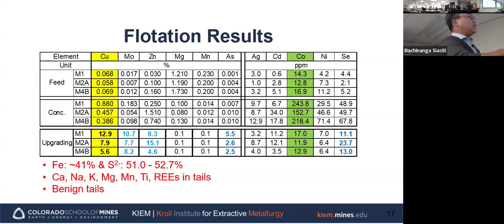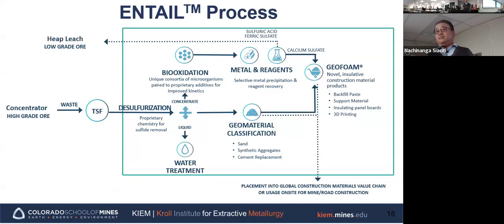And then, as you can see, I mentioned arsenic. Arsenic comes to the concentrate. So it is concentrated in sulfide and pyrite, along with moly, zinc, selenium, and other elements. As you can see, the cobalt is also concentrated to the several hundred ppm level. So we increase the metal content, sulfide, and sulfur, and all the other things are in the tail, including rare earths, because rare earths are mostly oxide. And we made a benign tail, so we use that benign tail to make some other product.